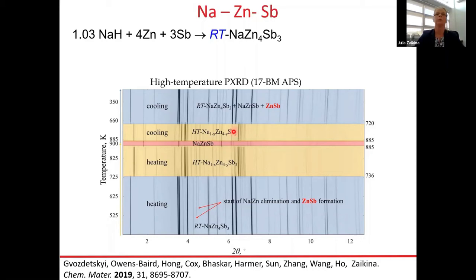And then on cooling, we did see that new compound coming back before it transforms back to the synthesized sodium zinc antimonide at 720. So we were very excited, but also very curious how we can stabilize this, what at that time looked like a high temperature polymorph of this 143 compound. So we targeted that composition and we did quench it from 800 Kelvin. However, we didn't see the formation of this high temperature phase.